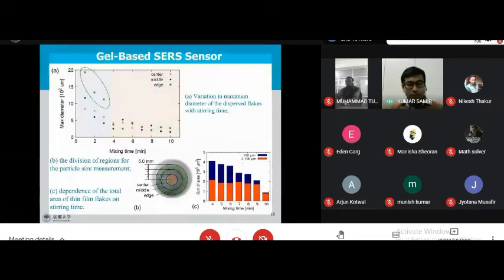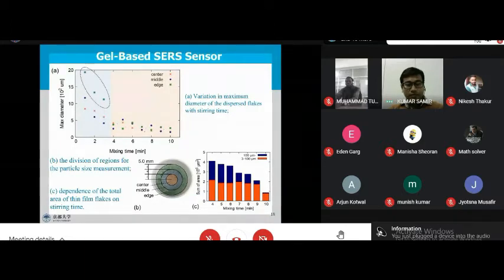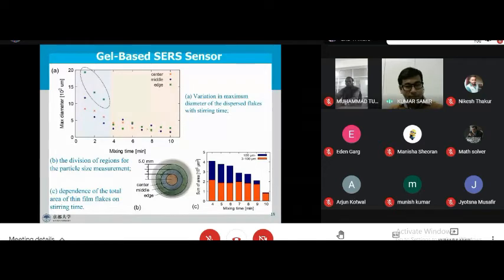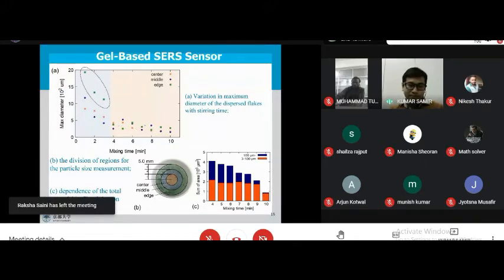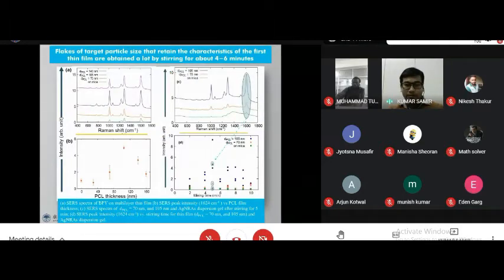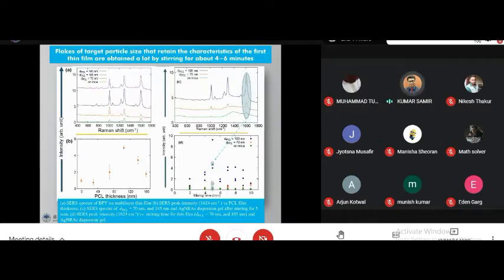What we observe is that with time, the average size of the particle decreases. Since there is a different centrifugal force at different parts, we divided it into three regions: center, middle, and edge. After around 4 to 5 minutes, all these regions have almost similar sizes. So we centrifuged our sample for around 4 to 5 minutes.